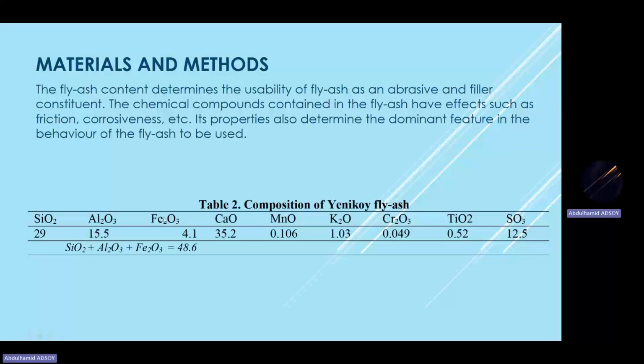These 3 chemical materials are abrasives, friction modifiers, and wear resistance increasing properties. So this composition of the fly ash itself has an effect on the outcome of the study. The reason we selected the Yeniköy fly ash is because the total amount of these abrasive, friction modifier and wear resistance increasing properties is about 50%. So it will give a good result in the study.